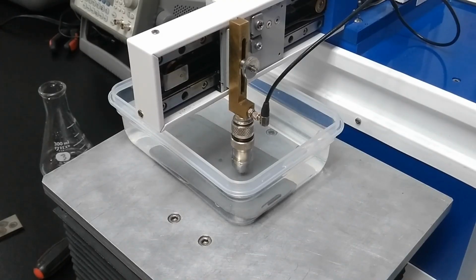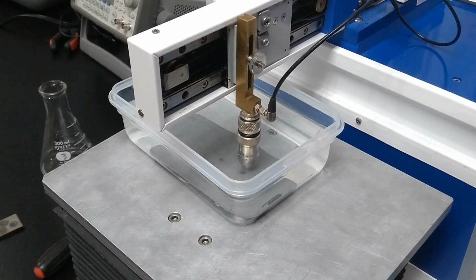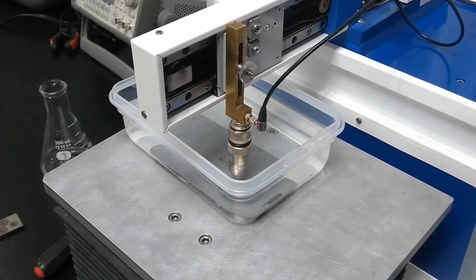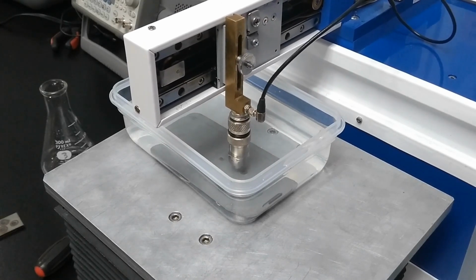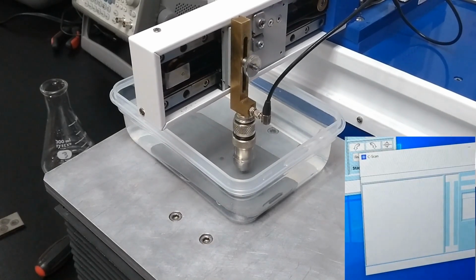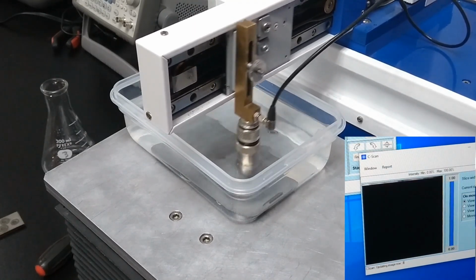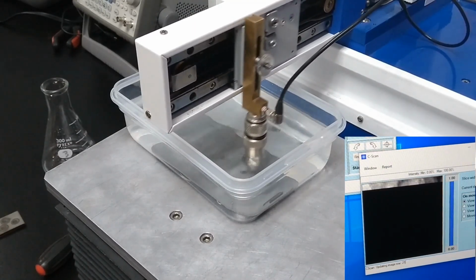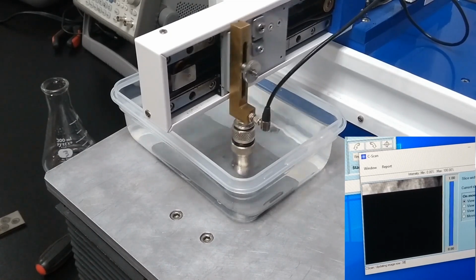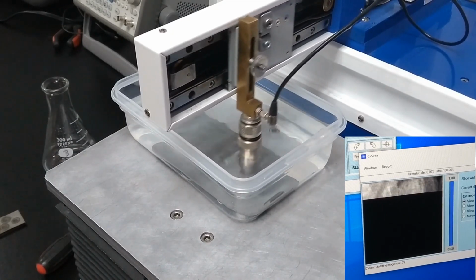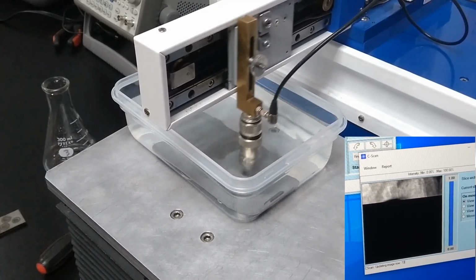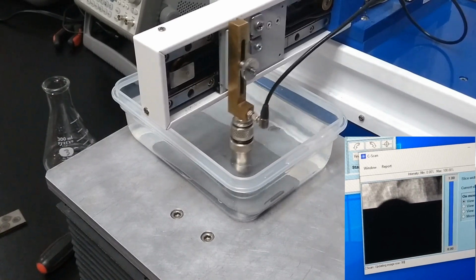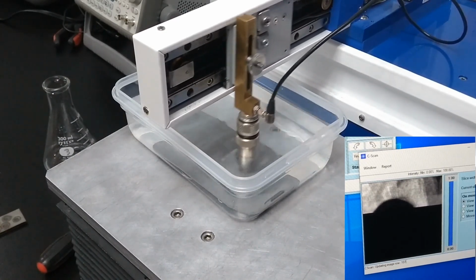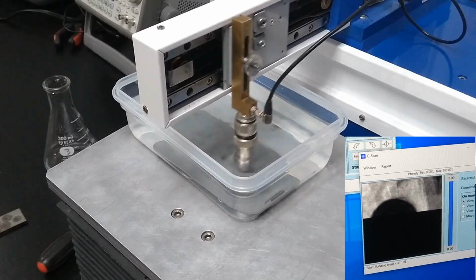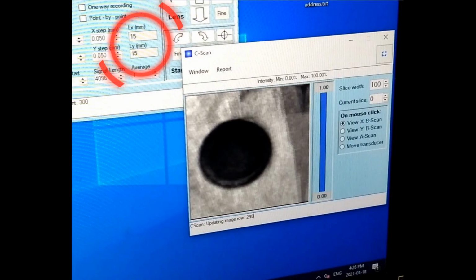For C scans, the transducer will move along the two horizontal axes. It will move quickly along one axis and slower across the other. For each stroke of the transducer, a line for the image is generated. The time to complete a C-scan is proportionally related to the number of lines in the image. The size, and thus the time required to complete, can be adjusted in the settings menu. In this demonstration, the scan area was set to 15 by 15 millimeters.